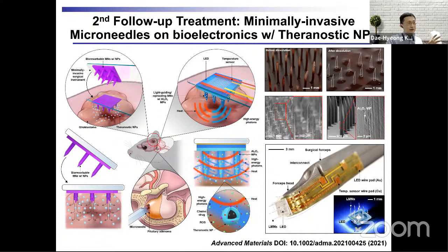So with just the microneedle, the light will be delivered in this vertical direction only, but using these embedded aluminum oxide microparticles, the photons will be scattered and spread over a larger area. So we can properly deliver UV photons to these theranostic nanoparticles. And also, the LED will generate heat, which will be beneficial for accelerated diffusion of the nanoparticles and also chemo drug. And of course, there is a temperature sensor which can monitor the thermal actuation process to prevent overheating.